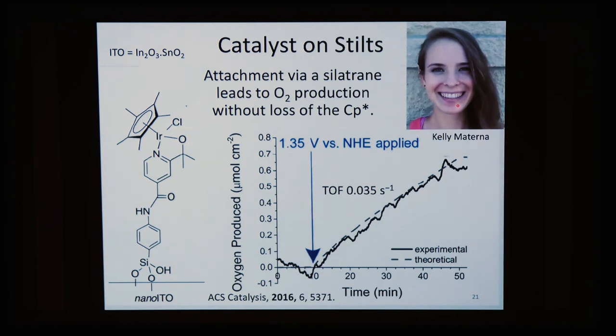And Kelly put the catalyst on stilts using a silatrane to connect the molecule to nano ITO, a conductive semiconductor. And when she did that, she found O2 production. And in this case, there is no indication of any loss of Cp*. And the probable reason is that the silatrane goes down with low coverage. Therefore, the metals are far apart from each other and do not chew each other up. So they're separated. And the turnover frequency is very low, far lower than the dimeric iridium-oxygen-iridium catalyst.